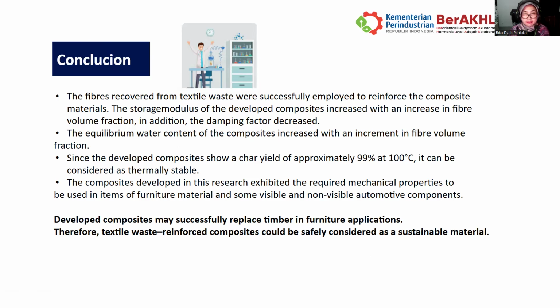Number 3, the developed composite shows a char yield of approximately 99% up to 100 degrees, which is considered thermally stable. The composite developed in the research exhibits the required mechanical properties to be used as furniture material and in some visible or non-visible automotive components. So the developed composite may be successful as a timber substitute in furniture applications. Therefore, the textile waste reinforced composite could be safely considered a sustainable material.